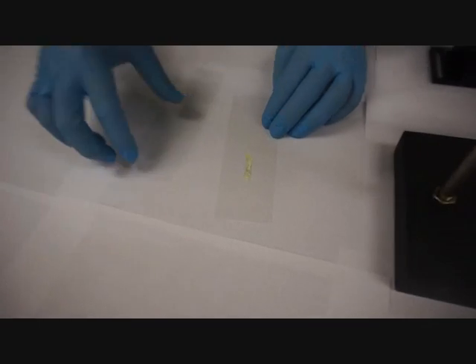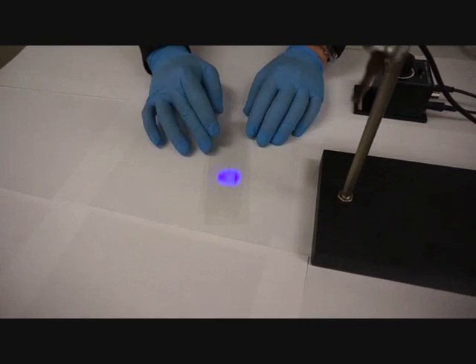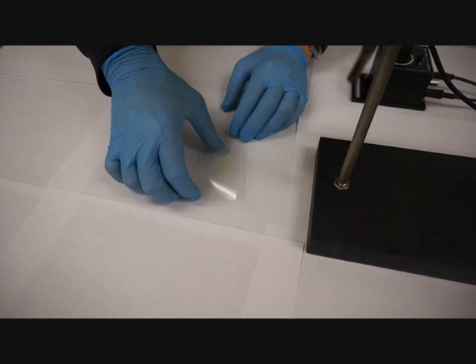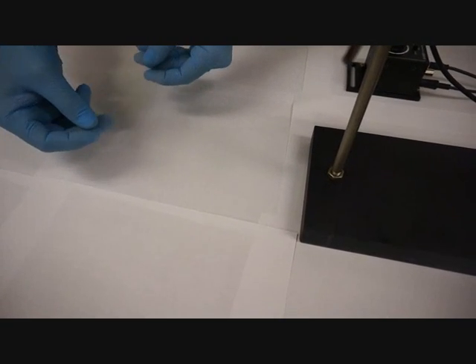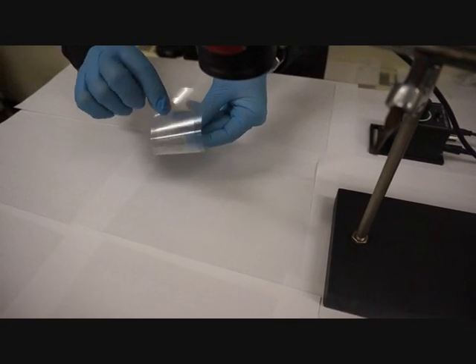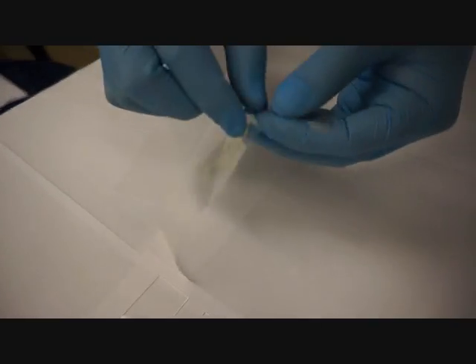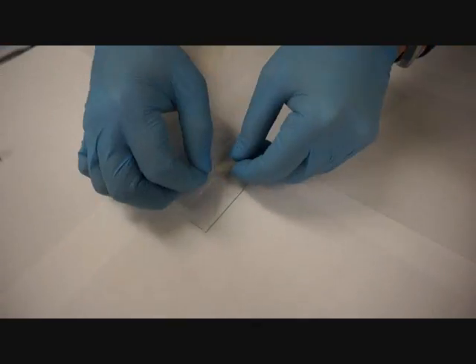Irradiating these resins between 2 surface-treated PET films with low-intensity UV light for a very short time results in partially polymerized films that are flexible and can be transported as rolls. At the point of use, the film can be peeled off, applied and irradiated for complete curing.